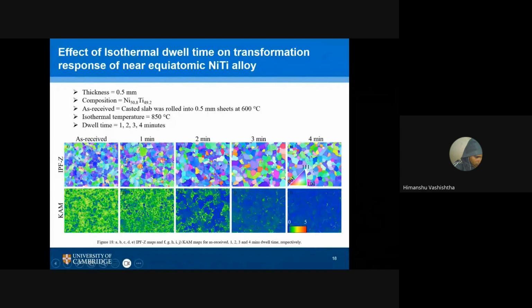That's called low angle grain boundaries. There are two types of grain boundaries, low angle and high angle. The usual convention is that most deformations or dislocations settle down at the low angle grain boundaries. So here, a lot of white lines in this analysis represent low angle grain boundaries, and the black lines represent high angle grain boundaries.